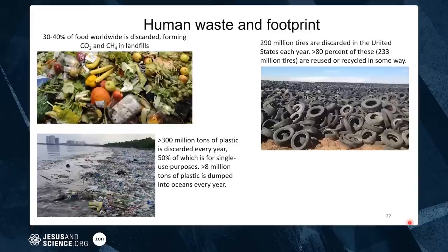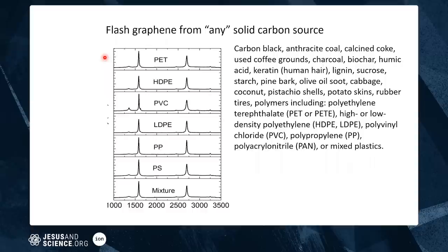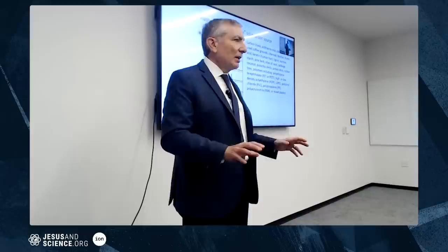How is this an environmental effort? Thirty to forty percent of all food is thrown out, and in landfills it forms not just CO2 but methane — a much worse greenhouse gas. There's also a lot of waste plastic and waste tires. All of those form graphene in the flash graphene process. Here are all the different types of plastics that humans use in bulk — we convert all of them, and the Raman spectrum confirms they've all been converted to graphene. You don't need to separate them — throw all the plastics together, flash, and you get graphene.